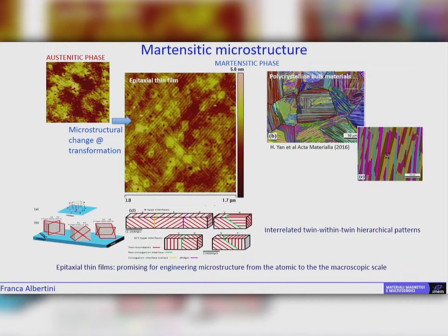Very important, as I already mentioned, is the microstructure of these materials. When we have the transformation from austenite to martensite, we have the martensitic microstructure that is a 3D pattern of interrelated twins. So it is possible, in principle, to engineer the microstructure from the atomic scale to the microscale by exploiting the connection and interrelation of the different twins.